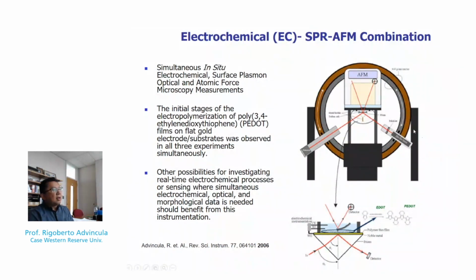So here we have the laser detector, we have the prism, we have the gold surface. In fact, the third component here, the gold surface, as shown here, is actually a working electrode in an electrochemical cell. Now, this electrochemical cell actually is sitting below this AFM. So we can have a cantilever tip that is close to the gold surface. And as we deposit the polymer, all 3 can be run simultaneously. So in this case, we can have an in situ, real-time deposition of the polythiophene monitored by AFM, electrochemical method, and SPR all at once.